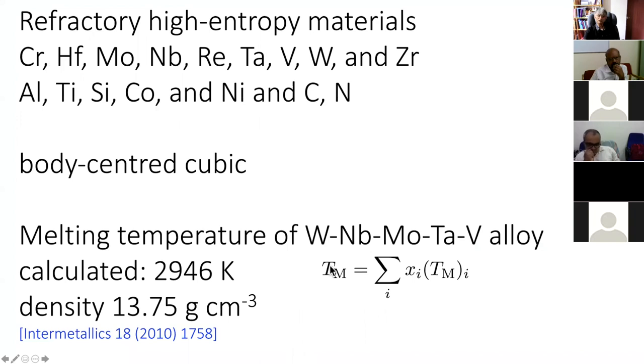Now, some people use a much simpler method, which doesn't have any proof that it works: that the overall melting temperature is simply the individual melting temperatures scaled by the concentration of the element. No evidence whatsoever that this works, because these calculations are done without comparing against an experimental measurement. So this is a refractory high entropy alloy, and the calculated melting temperature is 2946 Kelvin. But wouldn't it be simple to do a measurement using differential scanning calorimetry or some other method?